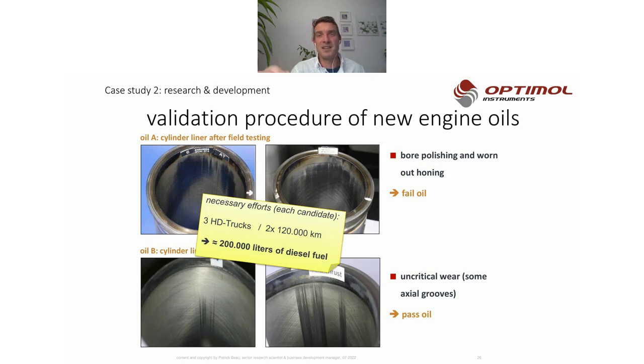Typically, and that's the basic investigation effort, if you would like to implement this combination, you need to run, it's also set by government and by standards, 3 of those heavy-duty trucks for 2 times 120,000 kilometers, because the oil change interval is 120,000 kilometers. You will waste close to 200,000 liters of diesel fuel, and you will end up, for example, with this oil number A in combination with a coated piston ring, a solution which is not suitable for your application. That's one of the examples why it's so beneficial to pre-screen it in lab scale.